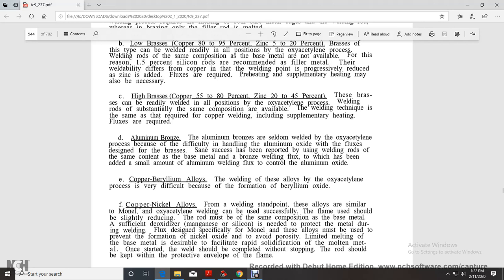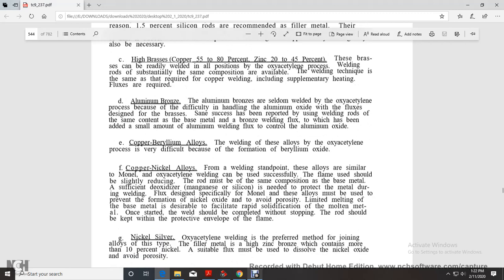Aluminum bronze can be welded with the oxyacetylene process, but it is difficult to handle because of aluminum oxide, so the flux is designed differently from that for brasses. Success has been reported using welding rod with the same content as the base metal, with a bronze welding flux to which a small amount of aluminum welding flux has been added to control the aluminum oxide. Copper-beryllium alloys are very difficult to weld by the oxyacetylene process because of the formation of beryllium oxide. Copper-nickel alloys are similar to Monel from a welding standpoint, and oxyacetylene welding can be used successfully. The flame should be slightly reducing.